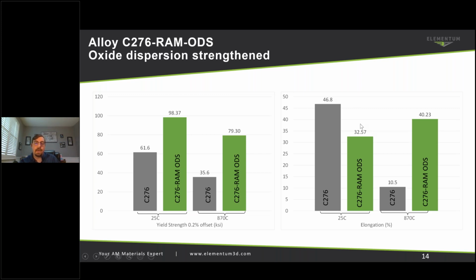But one of the things I did want to highlight here is that we're maintaining our ductility in a lot of these cases, where we're even seeing improvements in ductility compared to the wrought alloy alone when we're going to elevated temperatures. And so there's some benefits and some behaviors that are occurring that are beneficial that you might not even see with the wrought alloy on its own. So we're not just matching the alloy that existed, but we're also looking at improving upon that.